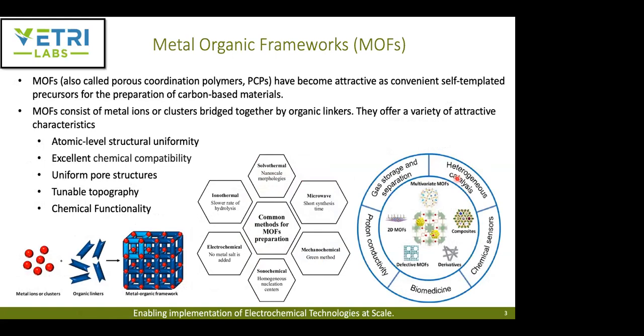Before going into that, here is an overview of metal organic frameworks. Metal organic frameworks, also called porous coordination polymers, are self-templated precursors for the preparation of carbon materials, as I mentioned earlier. They can be considered low-cost materials depending on the metal source employed. They are crystalline porous materials composed of both organic and inorganic components in a rigid periodic network structure. You can modify metal organic frameworks with binding sites, such as reactive nitrogen that can bind to the metal ions, and the metal ions and organic linkers undergo a reaction. Common preparation methods include solvothermal synthesis to get nanoscale morphology, a short synthesis route using microwave, and multiple other methods to produce these MOFs.